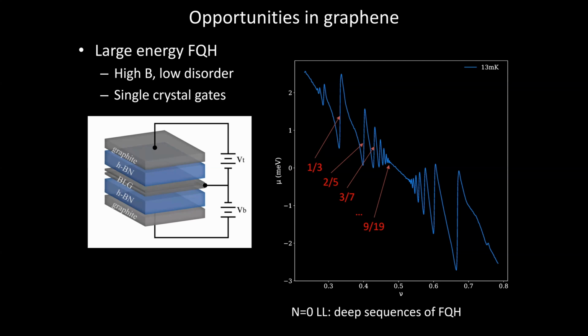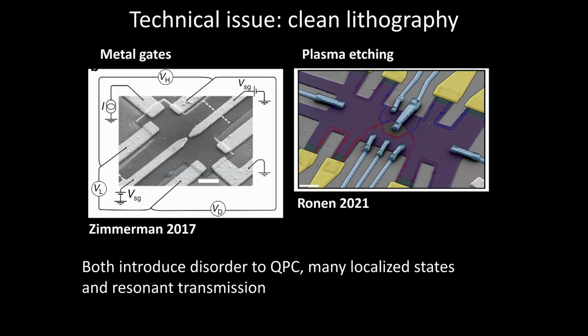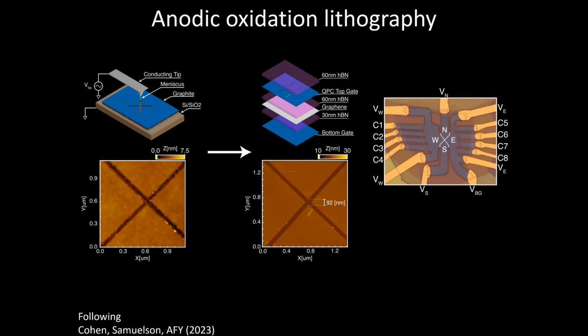including the gates. Now, this leads to a problem, which is that we'd like to be able to control electric fields on a very fine spatial scale. We'd like to be able to move where the edge states come here and there. And we can't actually do that if you have a single crystal of graphite. People tried by not using single crystals of graphite, and I'll leave this literature aside, but they made some progress, but it was always limited by the disorder introduced by how you fabricate these structures. So the thing that's enabled us to make some progress is a neat trick, which I'll describe, which is that it turns out you can pattern graphite in a nifty way.